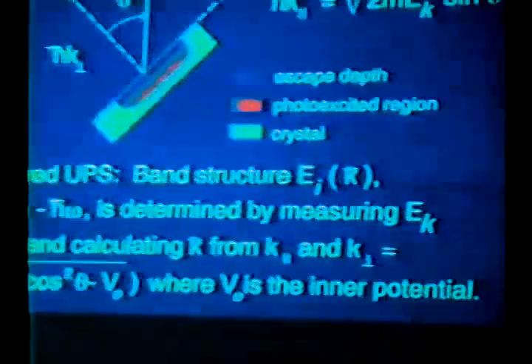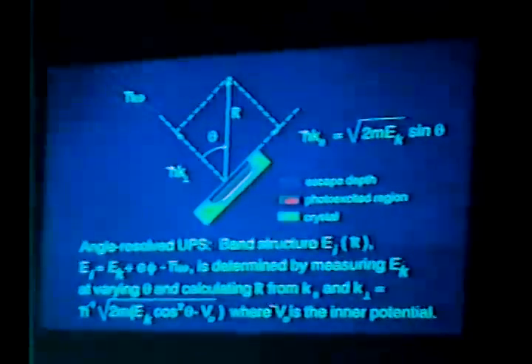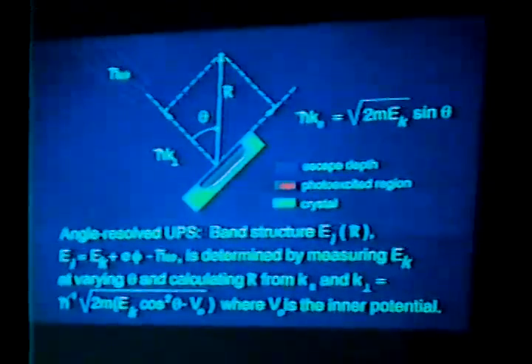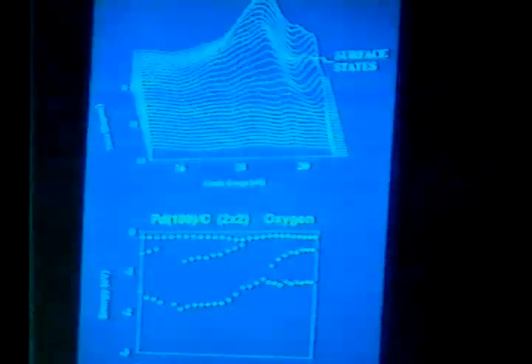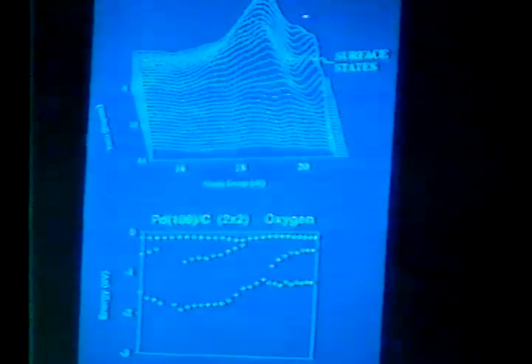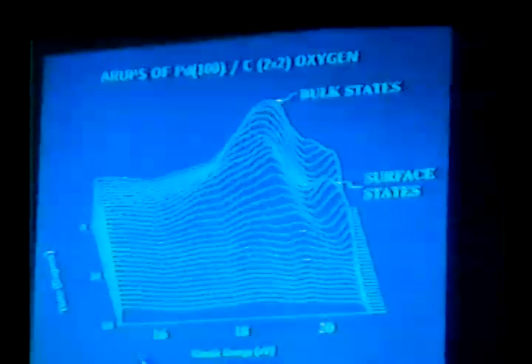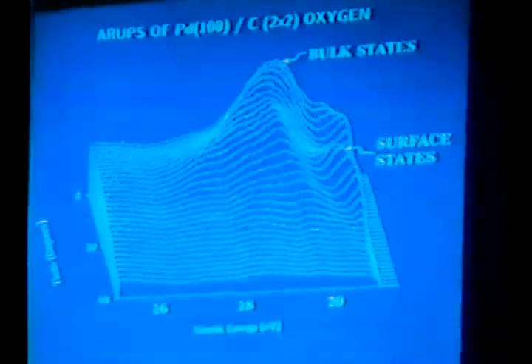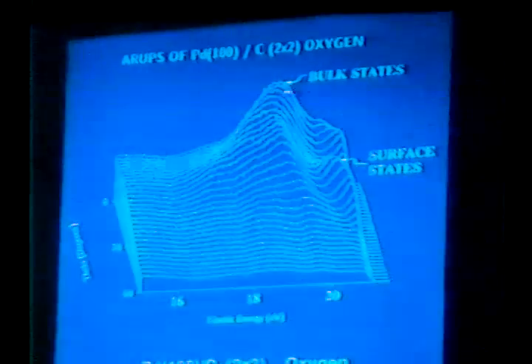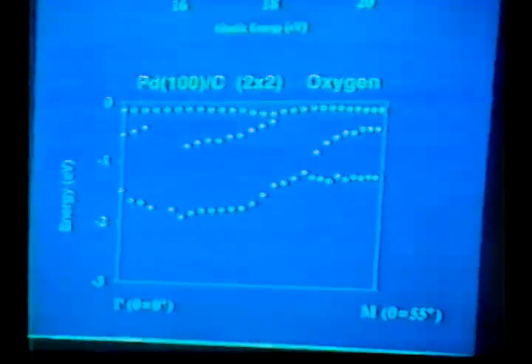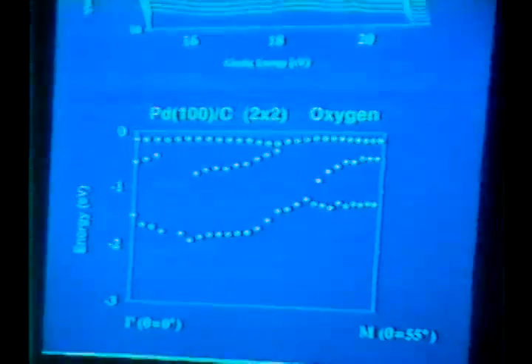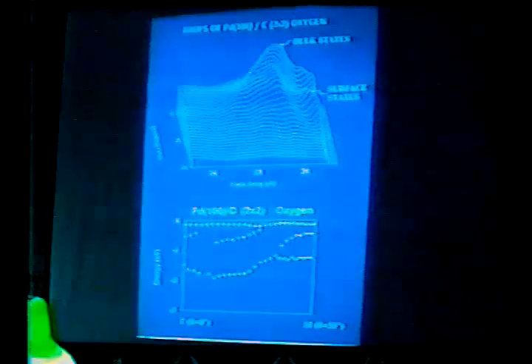It's angle-resolved valence band photoelectron spectroscopy done this time with a UV source, simply by measuring kinetic energy and the angle, the takeoff angle defined here. One finds what the parallel component of the propagation vector is in the crystal, and then one can also determine with a little bit more knowledge the perpendicular component by theoretically knowing the so-called inner potential V0.